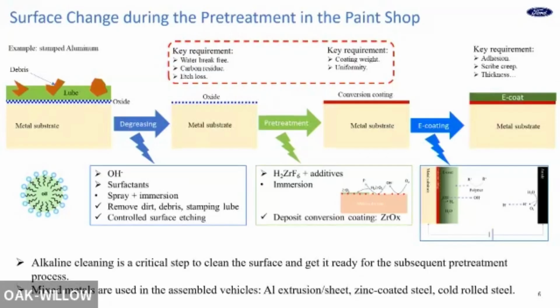So after this pre-treatment process, you can get a conversion coating on the surface, and the key requirements are the coating weight and the uniformity. Then the pre-treated part is sent to the E-coat bath. You apply potential and get some polymer deposited on the surface and cured. And you can see here the key processes for the new material in the paint shop are the alkaline cleaning and the pre-treatment. Especially the alkaline cleaning is the critical step to clean the surface and get ready for the subsequent pre-treatment. Now we know what's in the paint shop process.